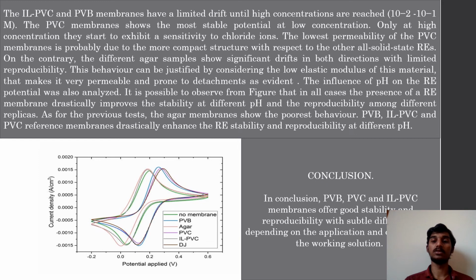The effect of pH on the RE potential was also analyzed. It is possible to observe from the figure that in all cases the presence of RE membrane drastically improves the stability in different pH and reproducibility among different replicas. As from the previous test, the agar membranes show the poorest behavior. PVB, IL-PVC, and PVC reference membranes drastically enhance the RE stability and reproducibility at different pH. In conclusion, the PVB, PVC, and IL-PVC membranes offer good stability and reproducibility with subtle differences depending on the application and on the pH of the working solution.